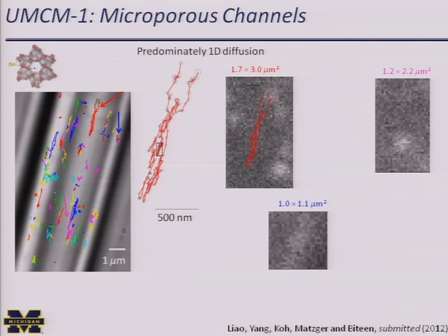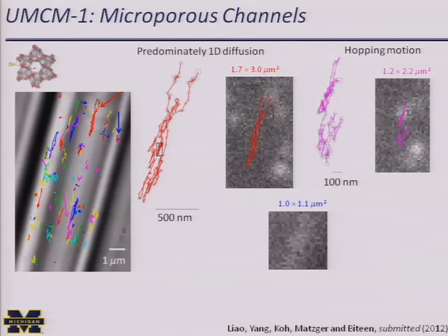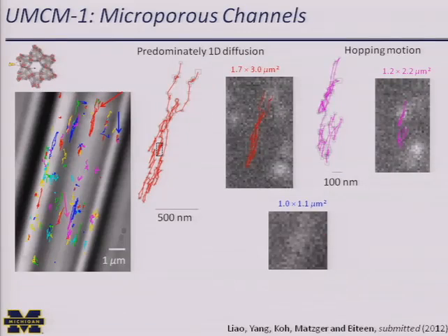On the other hand, if we look at this pink arrow, this trajectory here, we see a molecule that's confined, jumps, is confined, jumps again. And so this is a molecule that's doing some sort of hopping between channels. And we think what's happening is these channels have dead ends. So you can see, for example, here there's a nice long channel, but there's an end at either end. And so the molecule goes back and forth until it somehow manages to find its way out. And it can find its way out through these mesoporous cages.